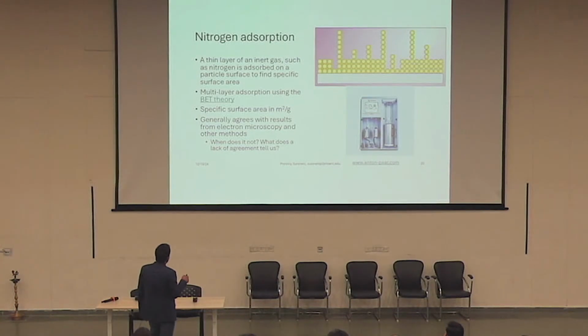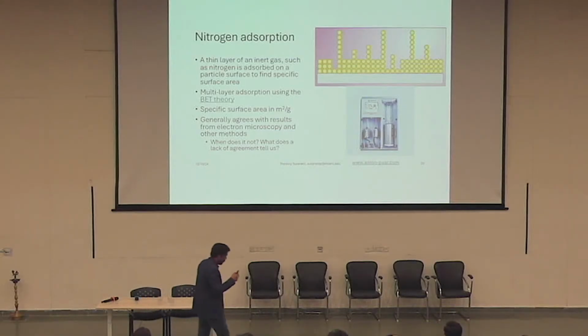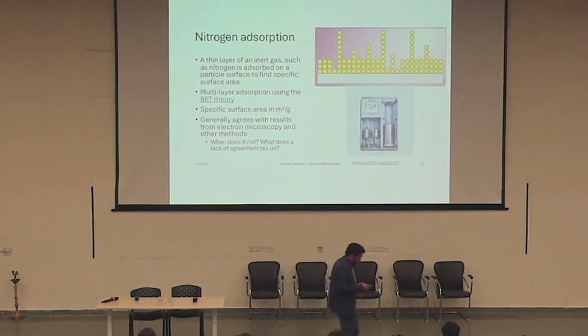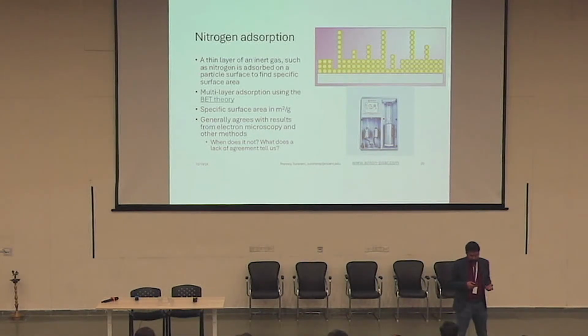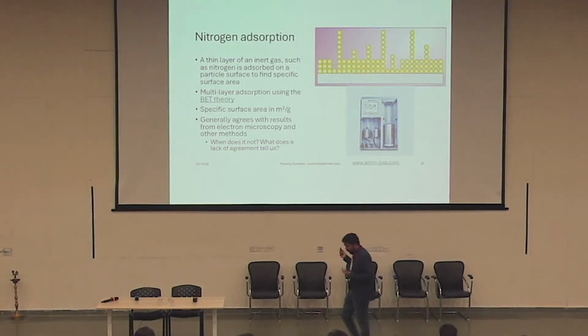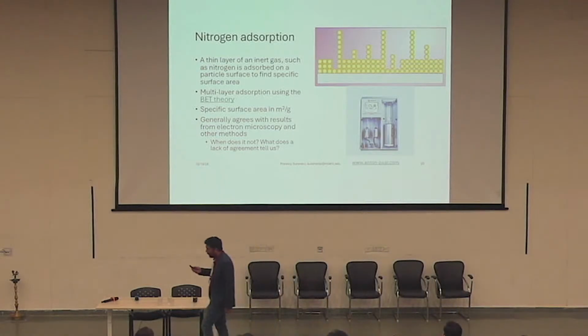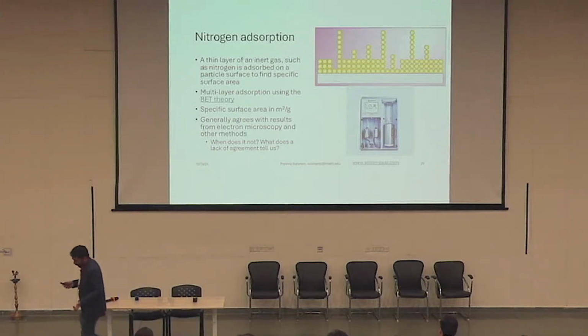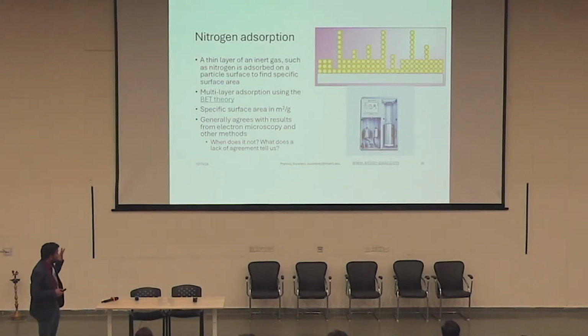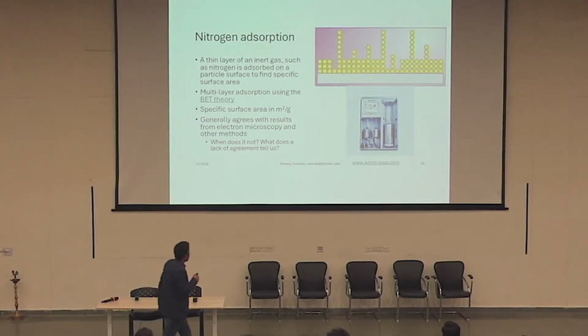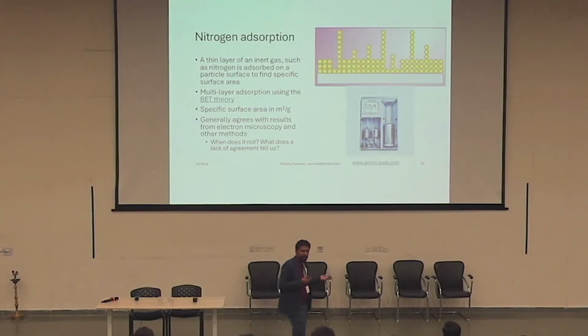So regardless, BET is basically a multi-layer adsorption theory. It's an extension of Langmuir and other adsorption theories. The theory, at least for me, is a little complex. I'm not a chemist, but you can work it out. But essentially, it links this adsorption behavior with a specific surface area. So you find out, and you use nitrogen. Can someone tell me why we use nitrogen? Why not use something else?